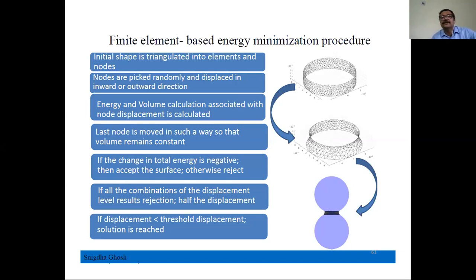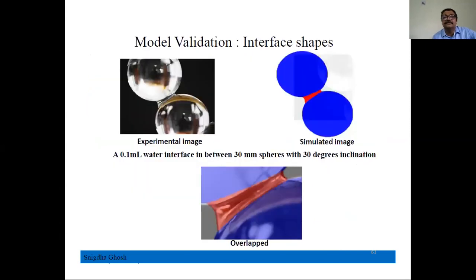So we did that, we did a lot of parallel computation, and I can tell you this is one experiment. Inclined, I don't know what the angle is. Okay, 30 degrees, and you can see the water film. You see this is simulated using the principles of surface tension and contact angle. These are the only values we use, and you see how good the fit is between the simulation and the experiment. Both are exactly matching. That means now we know from fundamentals how to predict.